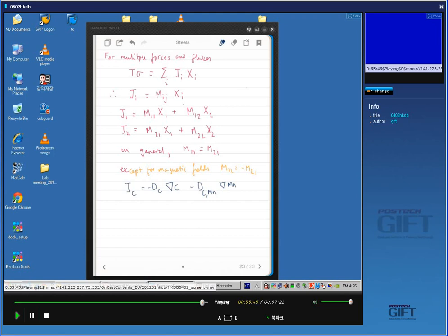And similarly, you can write that the flux of manganese will be minus the diffusion coefficient times the gradient of manganese, plus a cross term. Yeah. Now manganese is a large atom, carbon is a small atom, so manganese flux is not going to be influenced greatly by gradients of carbon. But on carbon, there will be a big effect if there is a gradient of manganese. Okay? So if I write an equation like this, you are now completely comfortable because you know where it comes from, right?